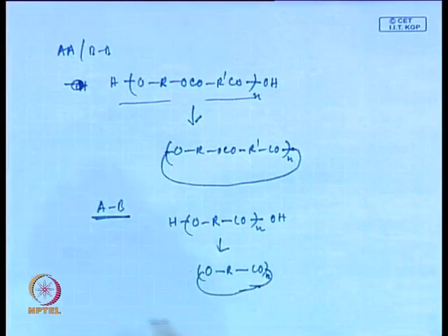If it forms cycles, these are low molecular weight, come out of the reaction, contribute to the lower molecular weight fraction, and increase your polydispersity. You cannot completely avoid cyclic formation; cyclics are always present in small amounts in a step polymerization. That is the reason your polydispersity goes up a little over 2.